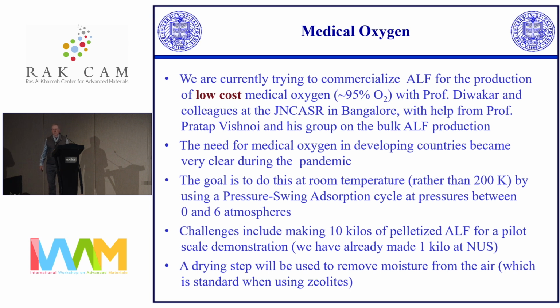The kind of immediate challenge is to make about 10 kilos of ALF, which Pratap is helping with, and also to pelletize it. We, in the lab, like probably nearly everybody here, make pellets one at a time in a pellet press. So if you've got 10 kilos of material and want to make pellets, that's not a very good way of doing it. So we need to find someone who's well set up to make pellets over there.